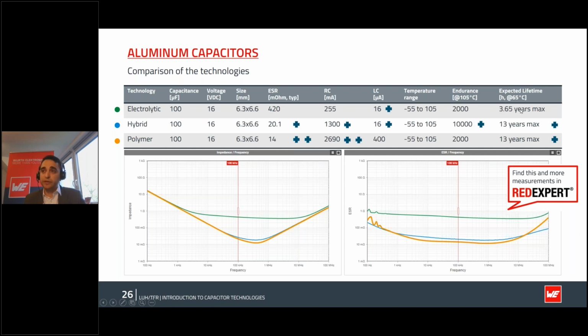However, if you do make a calculated lifetime scenario here at full ripple and 65 degrees, you can see the electrolytic part will last for about 3.5 years, and the hybrid and polymer will last for more than 13 years. And this is where we cut it off. We only specify more than 13 years. You can also see in the graphs below that in blue and orange, the hybrid and polymer parts are rather close together, and the electrolytic is a little bit further apart from that.